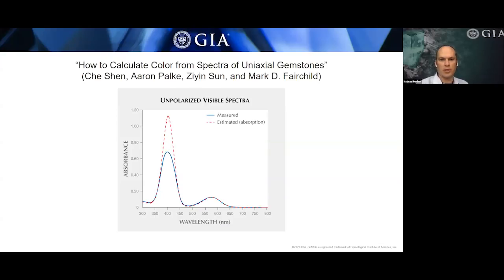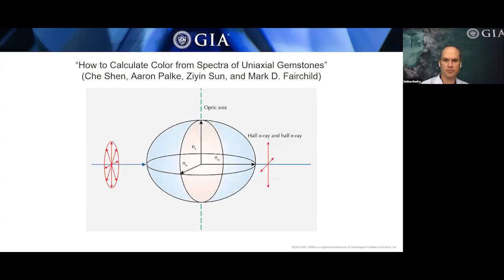So one of the problems that was encountered by the authors is that when they estimated the unpolarized spectra from the measured absorption spectrum, the estimation and the measured spectra did not agree with each other, and so they determined that the error was in the method of using absorption as the measuring technique. And so basically they remeasured the spectra in transmittance and added the spectra together in transmittance, and then were able to convert it to absorption and to eliminate this error.